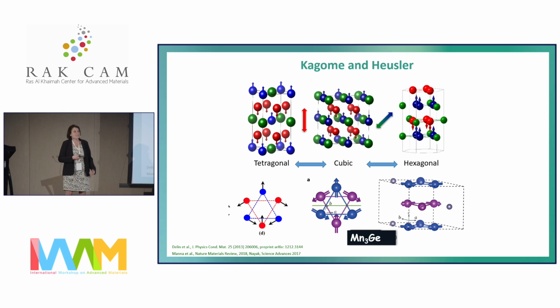So this means here we have a class of material where we have thousands of members, and very often we have in the phase diagram hexagonal and tetragonal distortion depending on the synthesis condition. So we can make this compound, you see here the triangles. So you have two Kagome lattices quite close to each other, so it's quite a three-dimensional structure. And so what we did, so this is one example, manganese-3 germanium or manganese-3 tin.